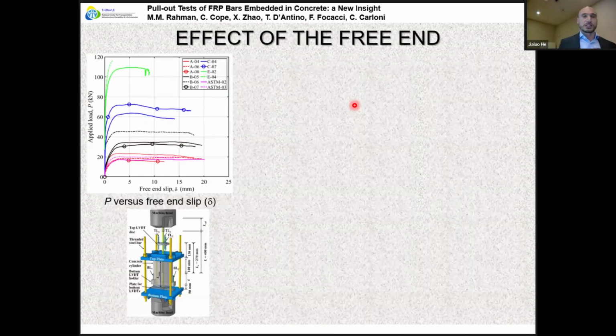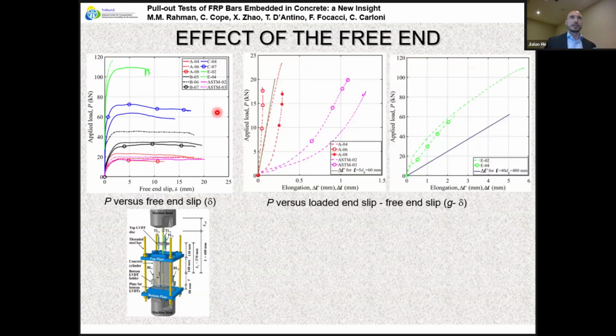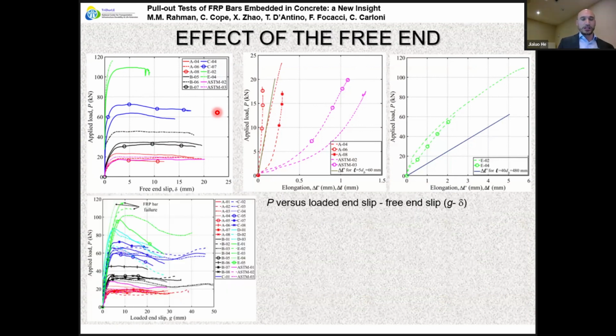Then we also measured the slip at the free end, and you can see that the slip starts to be noticeable at a different level of load compared to the peak if you change the bonded length. Then, by coincidence, we plotted something that started to make us scratch our heads. We plotted the slip at the loaded end measured from the LVDTs minus the slip at the free end, the difference between the two slips, which is the elongation of the bar.